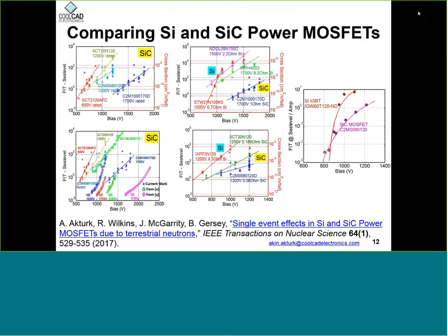You generally do this test at the higher bias, then you just extrapolate to lower bias. For example, at the 1200 volt part, if you try to do the test at 600, it will take forever. You cannot really get the data. The longer it takes to fail, the longer you need to run the experiment, so for almost all experiments it's not very practical to run anything at very low voltage. And in the case of silicon, at very low voltages you cannot really make them fail because there's a very hard threshold.